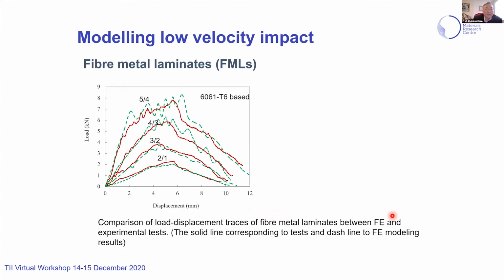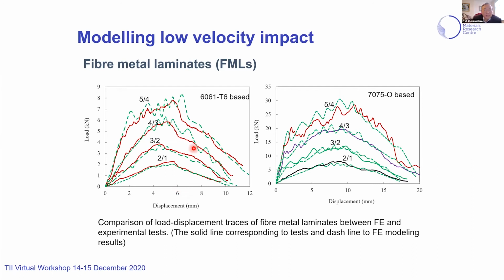I haven't mentioned the interaction. Of course, you have to define interaction between aluminum and composite, and you could also define interaction between plies. So these are the modeling results. We have the broken line from numerical modeling and the solid line from test. We can say we have achieved pretty good correlation. This is for two aluminum alloy based fiber metal laminates. Very good correlation.